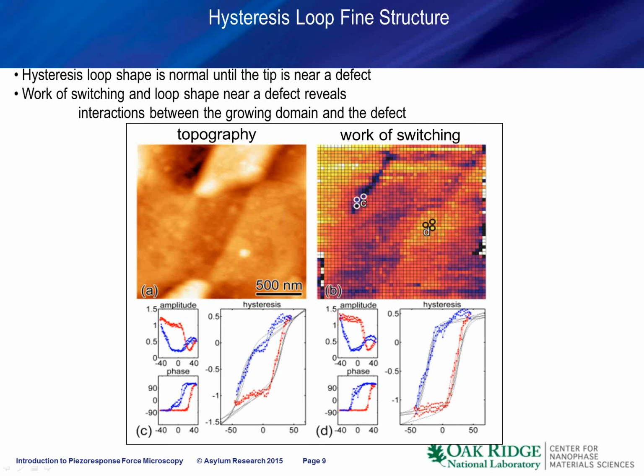For example, the 3 points in location C are acquired with the interval of 30 hysteresis loops. So all points in C have a very pronounced fine structure. All points in D have a less pronounced but very real fine structure. And points in other locations don't have this fine structure. So the reason why it happens is obviously because the hysteresis loop tells us something about the interaction between the growing domain and the defects pre-existing inside the material.